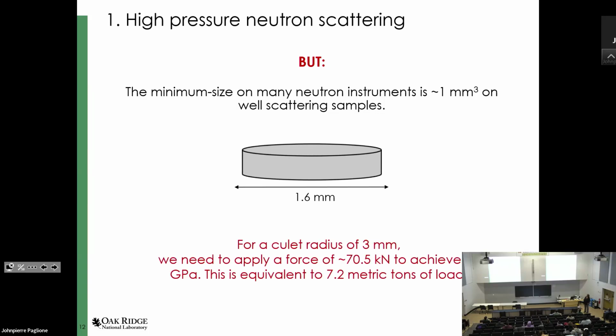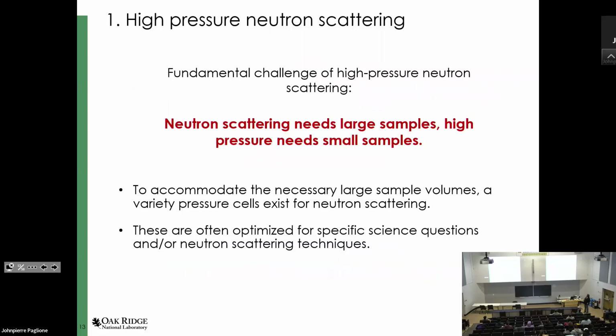So now to get to 10 GPa on a sample that can be contained in a diamond cell, you need 7 metric tons. So this means you're parking a big truck on your diamond cell. And this really means you need entirely different cells. You can't just have a little cell with screws that you tighten. And that really is the fundamental challenge of high-pressure neutron scattering. Neutrons prefer large samples, pressure needs small samples, and we are trying to combine these two things.